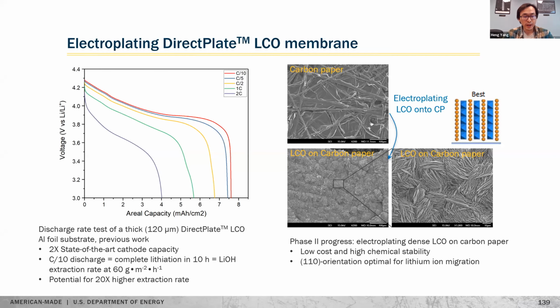So in our previous work, we have demonstrated a high rate discharge of a very thick direct plate LCO material. So here the LCO is 120 micrometers thick, at least double the current state of art in terms of lithium storage capacity. So the red curve is a C/10 discharge, which means a complete lithiation reaction in 10 hours. So this translates to lithium hydroxide extraction at a rate of 60 grams per meter square per hour. As you can see, we can further increase the operation rate to 2C, which means 20-fold higher extraction rate is possible if we don't have to utilize the full lithium storage capacity of the membrane.